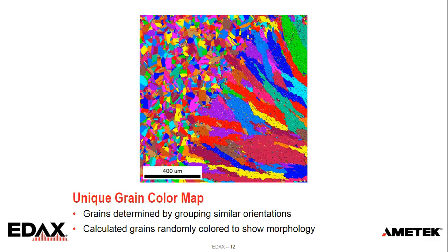Once we've determined the grains, we can then randomly color them. We call this a unique grain color map, or just a grain map. The colors are such that no 2 adjacent grains have the same color, so it really shows morphology, the size and shape of the grains. And again, we can see that the weld grains are a much different shape than the base metal.